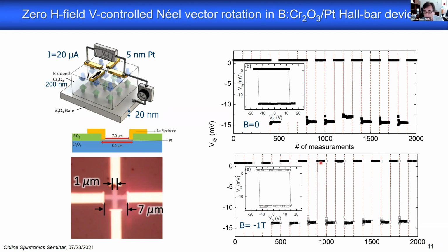Here you see the hysteresis curve. Here you see another experiment where we are in one state, take 100 measurements, then apply an electric field and the magnetic field that is always applied, switch into the other state, measure again 100 times without the field, apply the field again, switch back, and so forth. So we were happy. We thought we do what we typically would do in pure chromia and what the group in Dresden actually has also shown in chromia. But then I said, so now let's investigate. Let's show that when we remove the magnetic field, we should accordingly increase the electric field, that otherwise the switching doesn't happen. And then my postdoc reported something very strange.